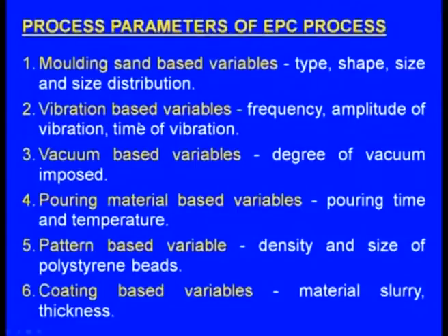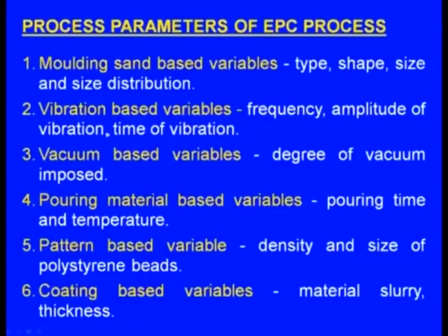Next one, vibration based variables: frequency, amplitude of vibration and time of vibration. After the sand is compacted inside the molding box, it is vibrated so that the sand settles down inside the molding box, because it is not a green sand, it is dry sand. That is why it is given vibrations. Now, the frequency of that vibration, amplitude of the vibration and time of the vibration come under the vibration